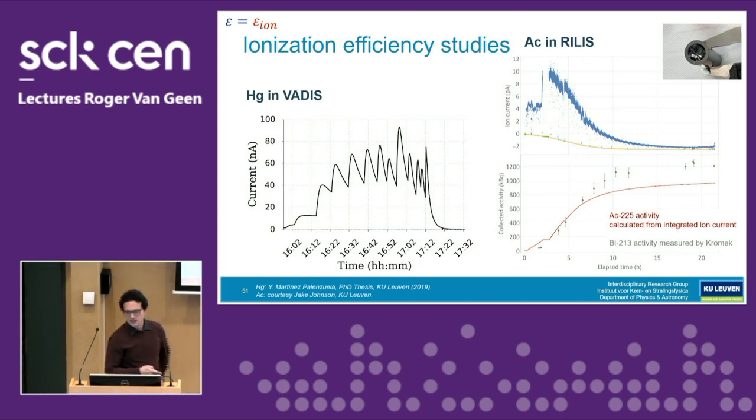At the end of this study, we also concluded we had about 10% efficiency, actually correcting for this little bit in green here after a few hours where we were stopped, and for the uncounted time before zero, we estimate that we could get to 13%.